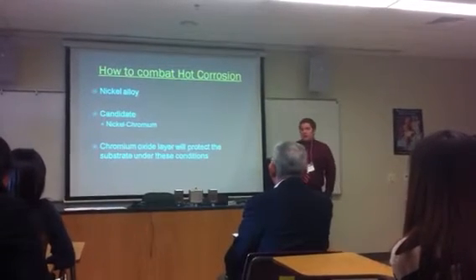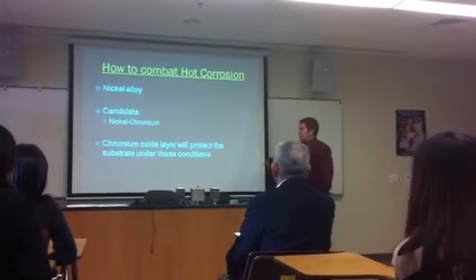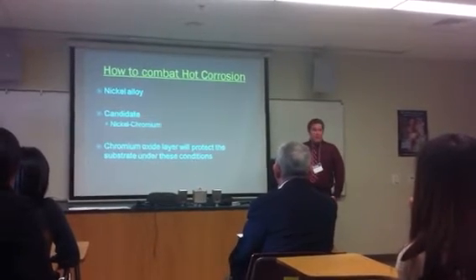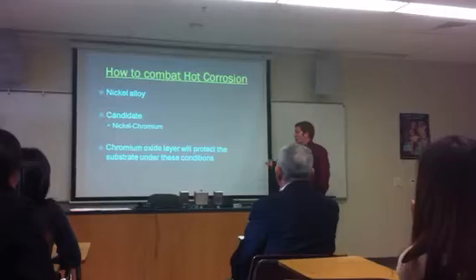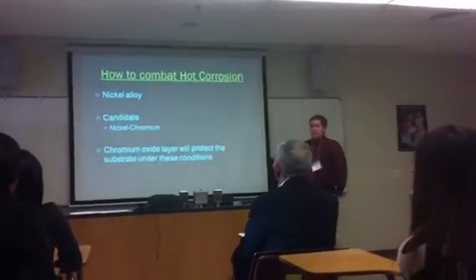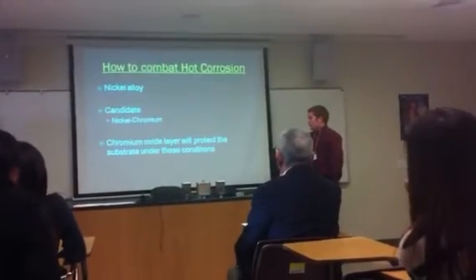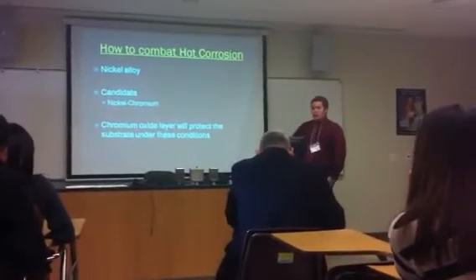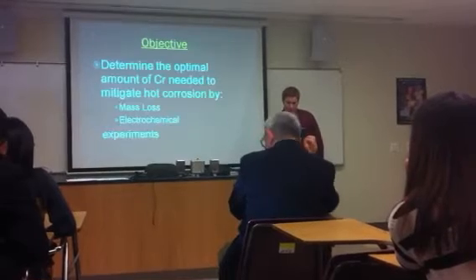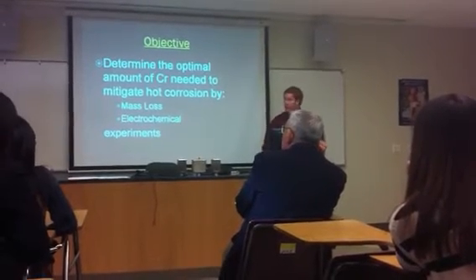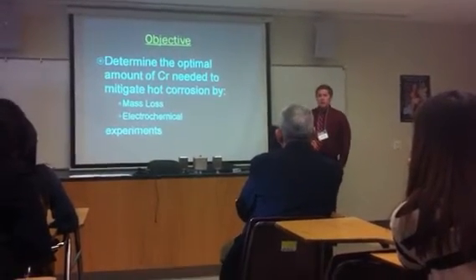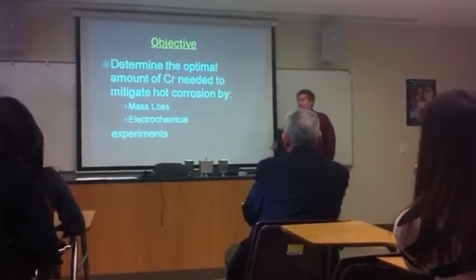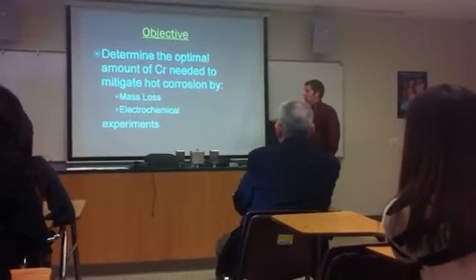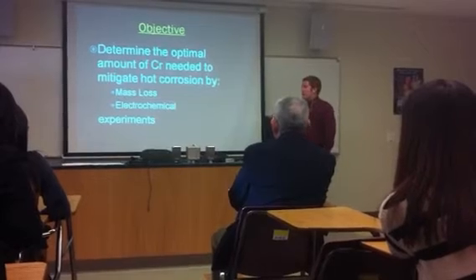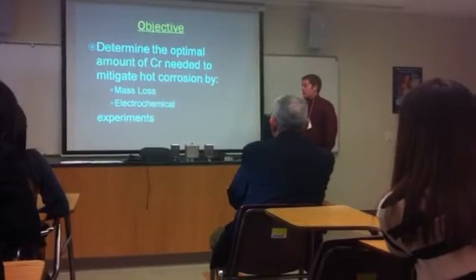So a likely question would be, how do we combat this hot corrosion? First of all, we know we want to use a nickel alloy because of its mechanical properties at these high temperatures. And a perfect candidate would be nickel chromium, because the chromium would help prevent the corrosion. So like it says here, the chromium oxide layer will protect the substrate under these high operating conditions. And moving on now, our objective is to determine how much chromium is necessary to get the optimum protection to mitigate this hot corrosion. And we're going to do this by a mass loss experiment and electrochemical experiment.